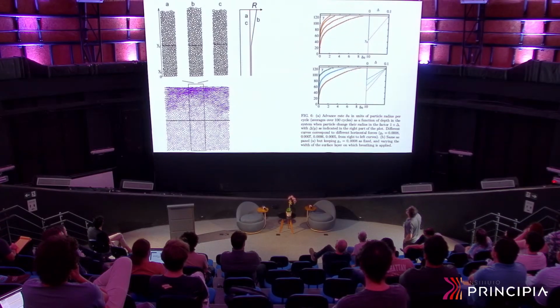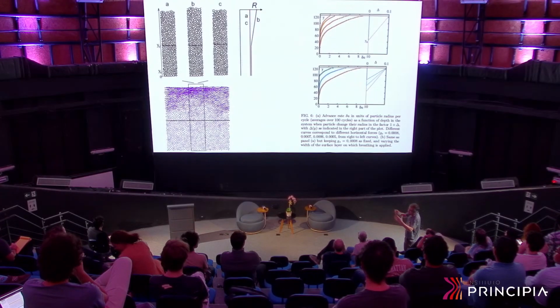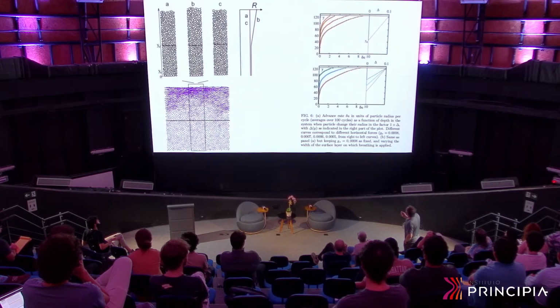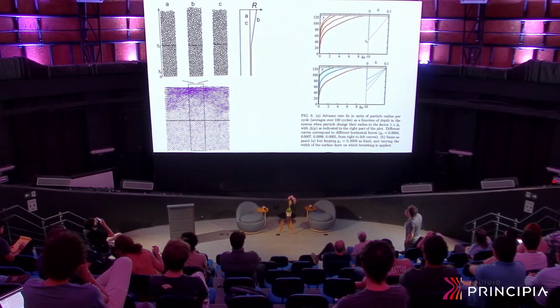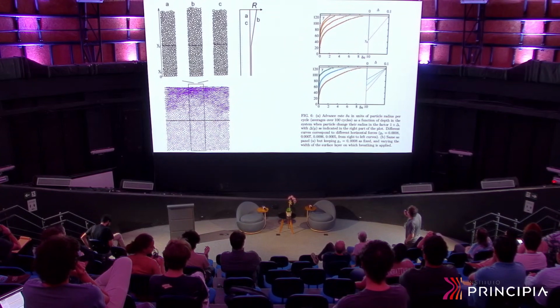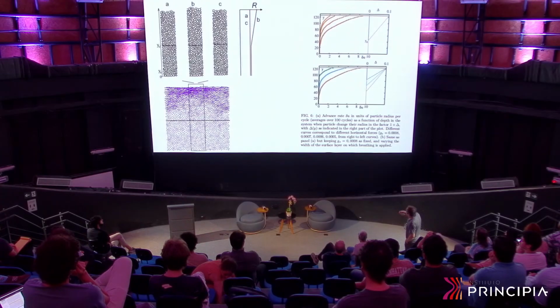As here, for instance, this is the profile that we use for the change in the radius, and different curves correspond to different amplitudes, some fraction of the radius itself. You see that essentially you observe the phenomenon in the region where the radius has changed, but there is also some interesting tiny phenomenon: below the value y naught here, some particles that are below even have a drag because of the particles that are above, even if their own radius didn't change, okay?